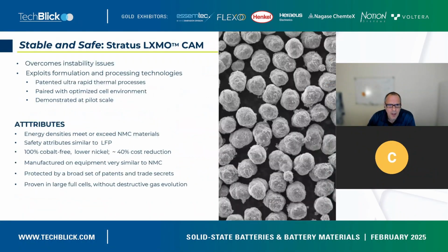So what we have done at Stratus over the past 3 years, this sort of started as a side project during COVID for me and has evolved into this company now. We have found that a super fast thermal process, so a very fast quench process, specifically at the very end of the process, creates a stabilized crystalline system in the material. And this can be applied both to more traditional PCAM, spherical co-precipitated precursor base material, as well as single crystal material. And if you can figure out how to get that stabilized material into a good densified thick format electrode, you can absolutely create batteries that compete very favorably with existing technology.